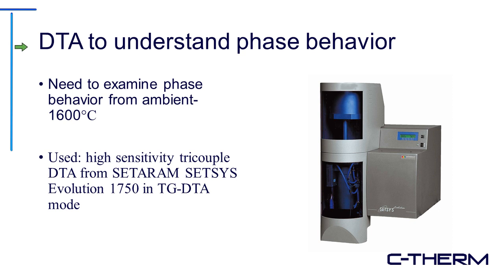The technique that was used was called differential thermal analysis, or DTA. It's a very powerful technique for identifying phase transitions in materials. So the technique that was used in particular was a high thermal sensitivity tri-couple DTA process. Tri-couple DTA uses 3 thermal couples instead of the classical 1 thermal couple, and because they're arranged in a pile, the sensitivity is additive. So you get about 3 times the sensitivity of a classical DTA technique,